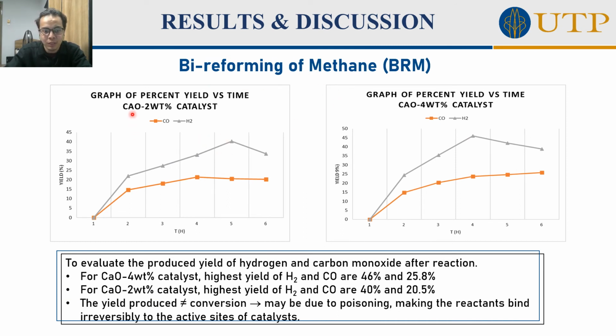So from the graph here, this is the graph of percent yield versus time for CaO 2% catalyst, and this one is the same graph for CaO 4% catalyst. And this is to evaluate the produced yield of hydrogen and carbon monoxide after reaction. And as you can see, in both figures, in the first hour there is no yield at all. It is because even though there is conversion, as you can see in the previous slides, there is conversion in the first hour. Probably the yield is still not there and it cannot be detected by the GC.